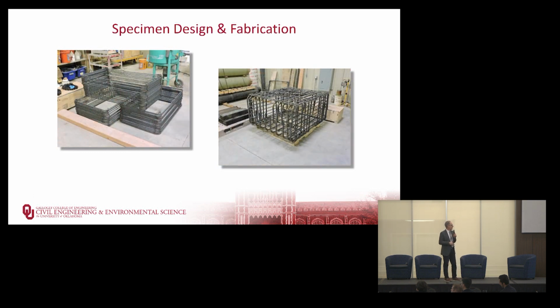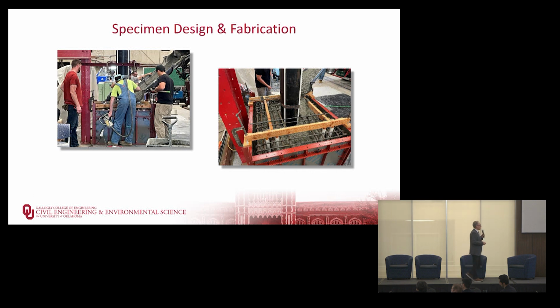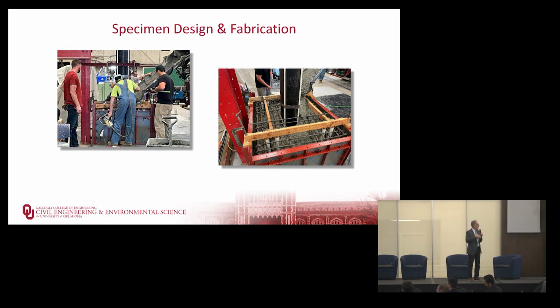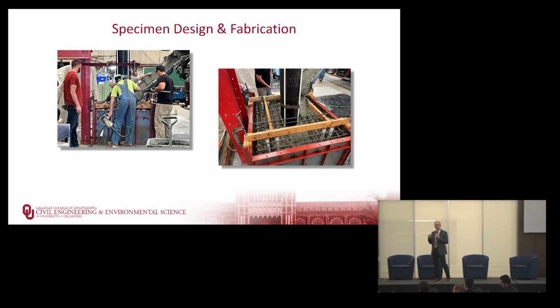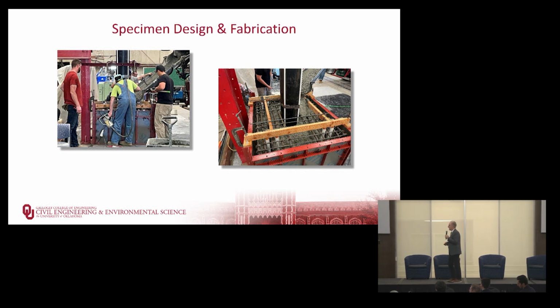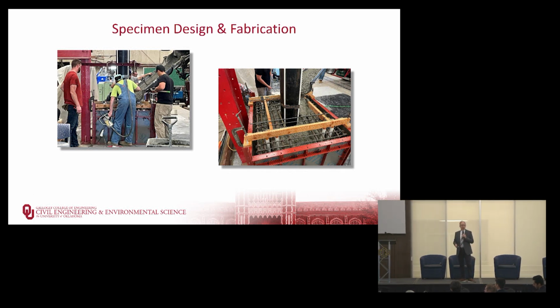And then a reinforcing cage for the base. So we built our formwork for the base, we put in a rebar cage, we put in our steel column at the right depth of embedment. Typically it's right now 1.6 times the diameter is the standard. Some of our research shows a little bit bigger value, but you want to make sure that steel tube doesn't pull out of your foundation. Cast the concrete for the base,